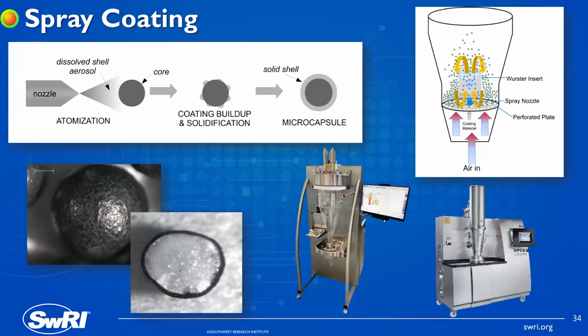If you want to go to a core shell capsule, that's where we move to spray coating. So you're basically spray painting a particle. So you have to start with a solid particle. This isn't going to work with liquids unless you first encapsulate that liquid into a solid particle. And then we're slowly building up a coating. So a classic is fluid bed coating or Wurster coating, where you're flowing solid particles around in a chamber of air, kind of like a lottery ball or a bingo ball machine, but much smaller particles. As your particles float around, you spray in, typically from the bottom for something like a Wurster process. The longer you spray, the thicker the coating.